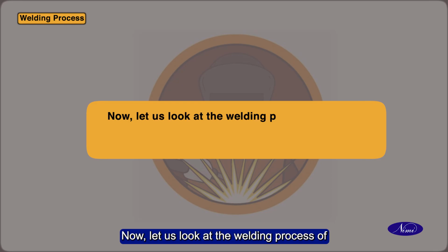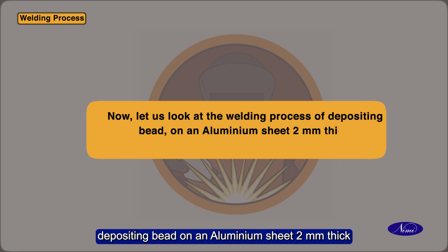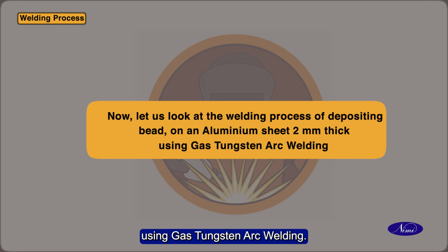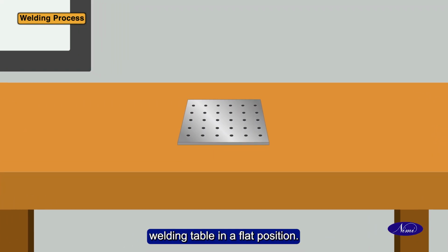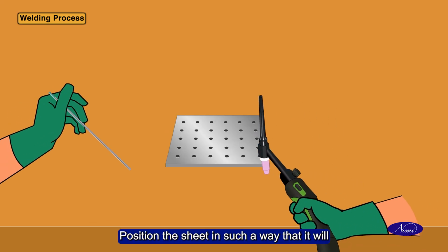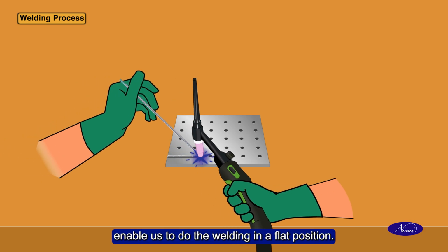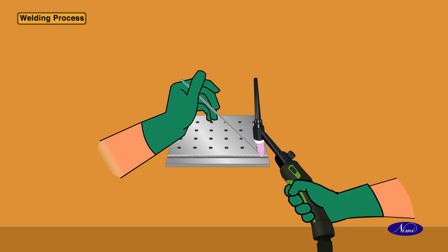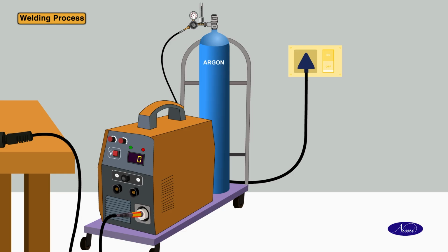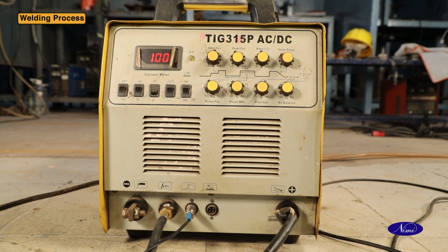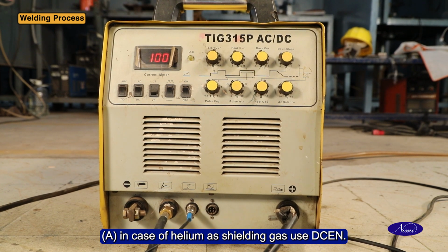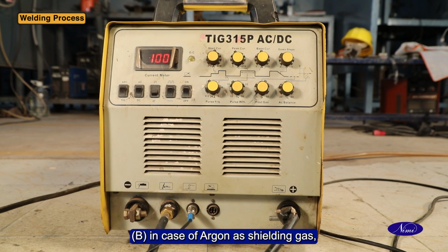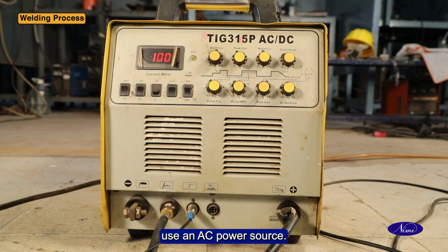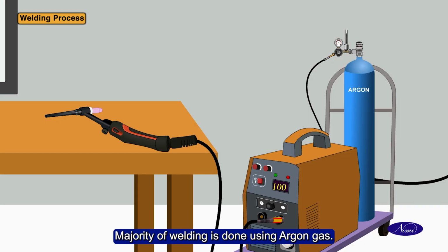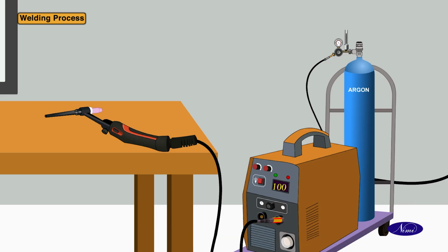Now, let us look at the welding process of depositing bead on an aluminium sheet 2 mm thick using gas tungsten arc welding. Keep the aluminium sheet on the welding table in a flat position. Position the sheet in such a way that it will enable us to do the welding in a flat position. Set up the gas tungsten arc welding machine. Select the power supply as follows. A. In case of helium as shielding gas, use DCEN. B. In case of argon as shielding gas, use an AC power source. Majority of welding is done using argon gas. Keep the argon cylinder next to the machine in a trolley at a safer distance.